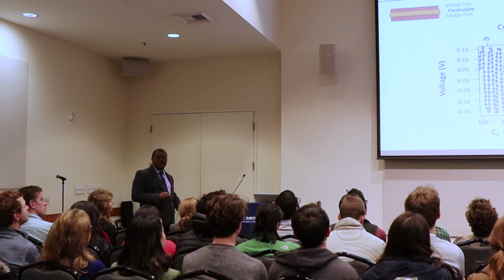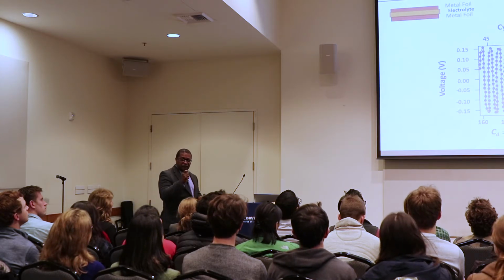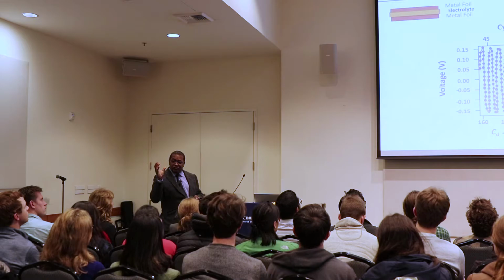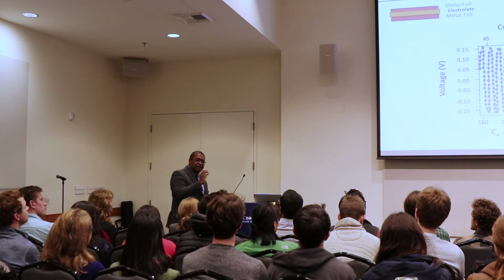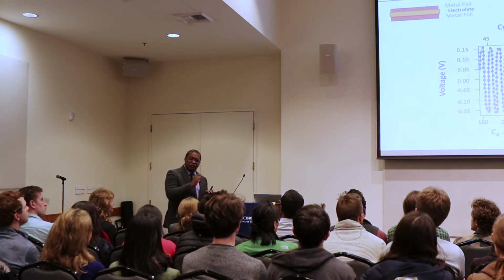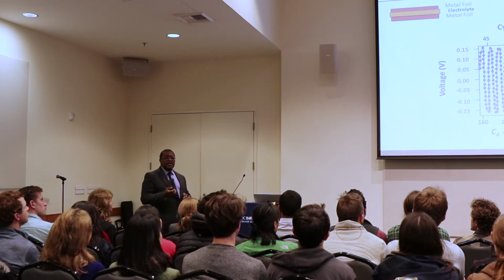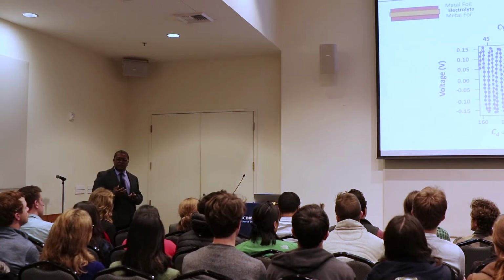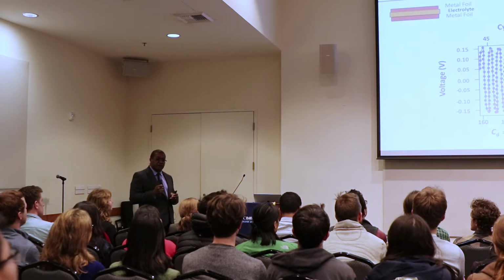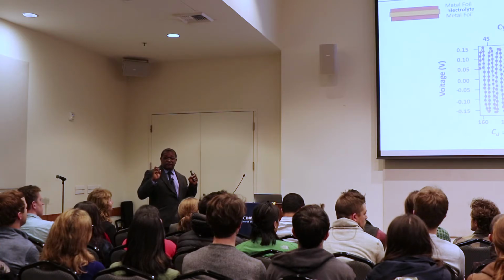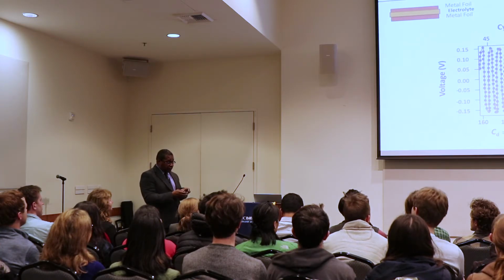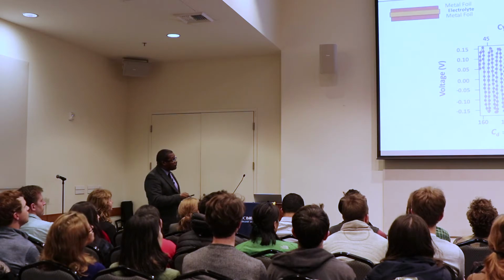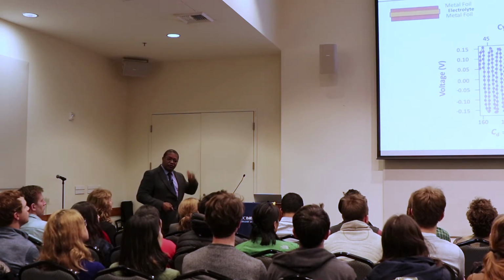So what you do is galvanostatically, which means at fixed current, you strip metal from one electrode for a period of time and dump it on the other one. After you're done, you do the reverse. The thinking is that if I measure the voltage, because this is done at constant current, if the resistance remains the same, then the peak-to-peak amplitude of the voltage response should actually be the same—it should follow the current.